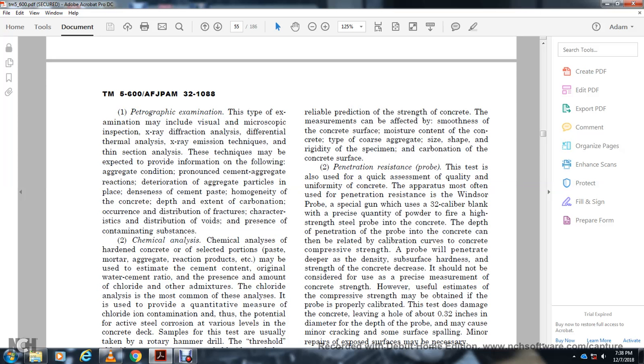the moisture content of the concrete, the type of coarse aggregate, the aggregate size and shape, rigidity, and especially the carbonation of the concrete surface. Penetration resistance of the probe test is also used for quick assessment of the quality and uniformity of the concrete.